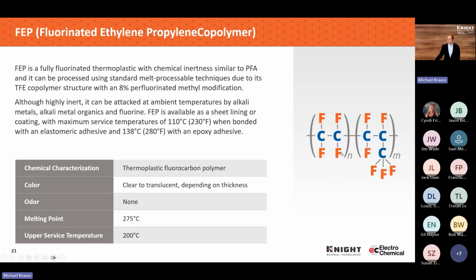And FEP is a copolymer of that TFE unit, the same one unit that we saw with the ETFE, and then we'll see with the other materials, and this HFP unit here with the 3 carbon chains and the 6 fluorines. It gives excellent chemical protection. The area that we don't see it used is in the high purity area. Most of the resin suppliers have focused on making high purity PFA grades, but from general chemical resistance, it's really good. The only caveat is that in hot HCl service, you tend to see surface blistering form with FEP, and you won't see it with some other materials. But it's a really good solution. It's a little less expensive than PFA, so where it can be used, it makes sense.